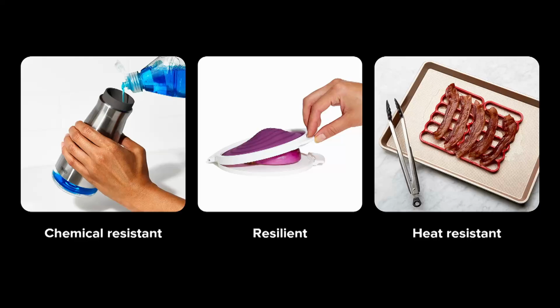One of the most important properties that we look for in silicone is its resistance to stress relaxation. If you handle a part, you'd know it immediately. You'd probably describe it as springiness. So it's the reason a silicone part and a part maybe you printed in Formlabs Elastic resin might have the same durometer, but they just feel totally different. The silicone is more resilient.